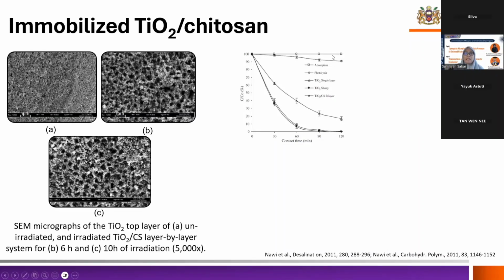Okay, and then we did a control experiment where we compare the activity of the photocatalyst with adsorption and also photolysis, using phenol as the pollutant. And we see that there is no photolysis. Photolysis means that only in the presence of the pollutant and the light irradiation, without the presence of the photocatalyst, we observe there is no degradation occurring. And the adsorption is only very little. So this means that phenol is not really adsorbing onto the chitosan or titanium dioxide.